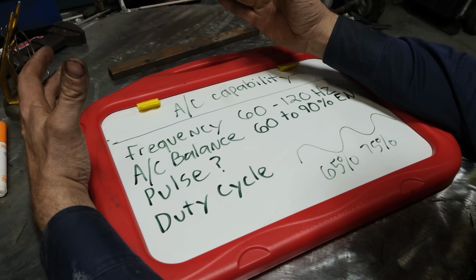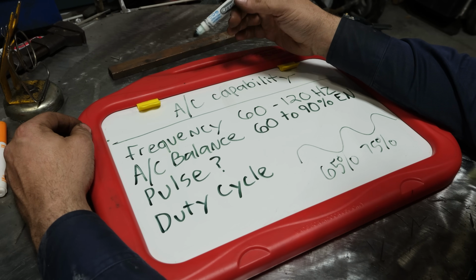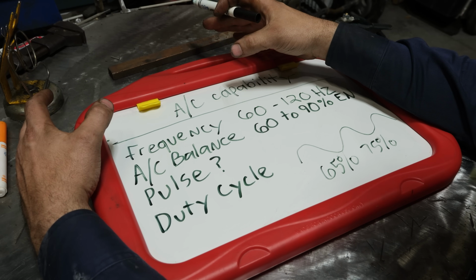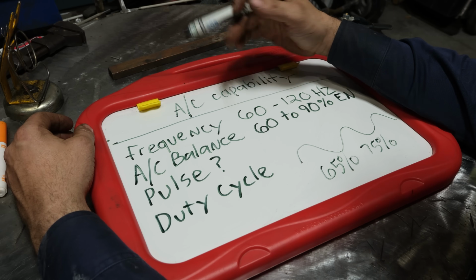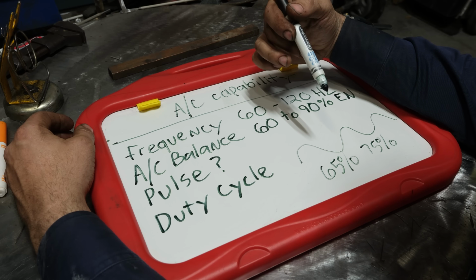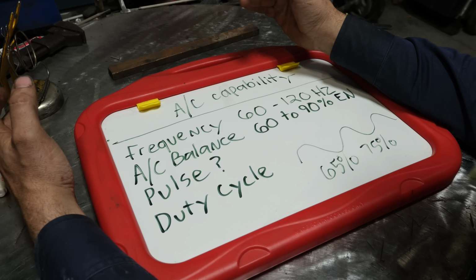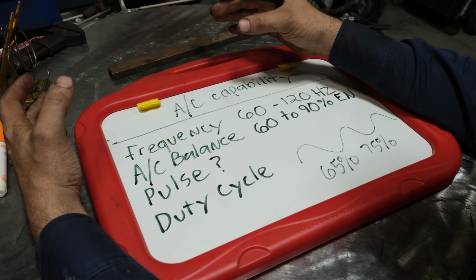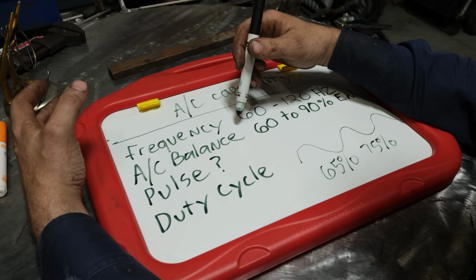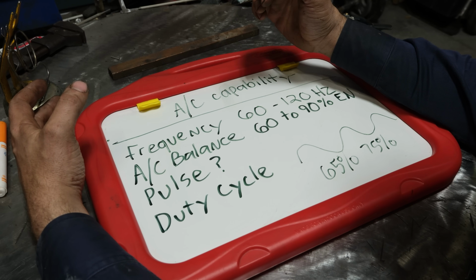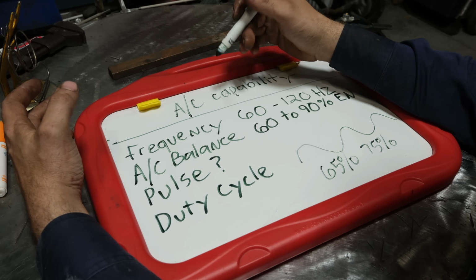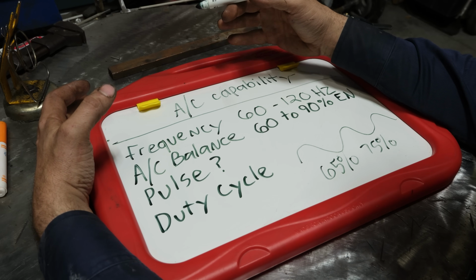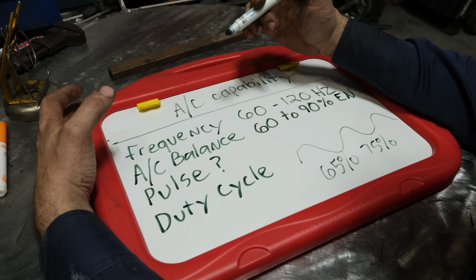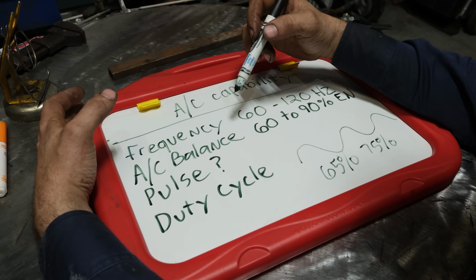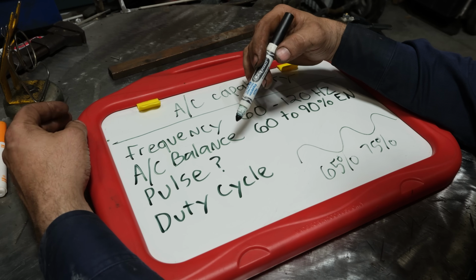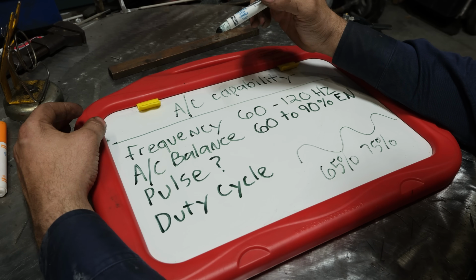Now, pulse, very hot topic with aluminum. For you beginners with a 200 amp machine, pulse is irrelevant on aluminum. That's my opinion, and I'm sticking to it. Aluminum has a property called hot shortness, where when you heat it up hot and then let it cool fast, it cracks. When you introduce pulse with AC welding and you don't know what you're doing, you will produce cracked welds whether or not you see it, and they will fail on you. So my recommendation is do not use pulse with AC.